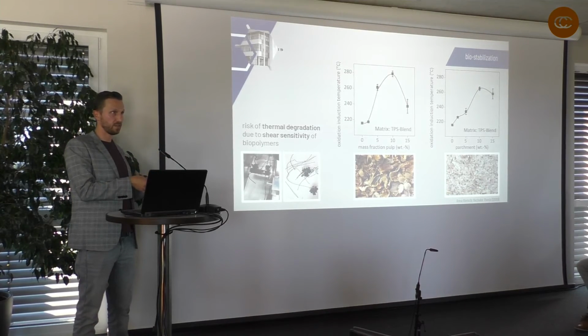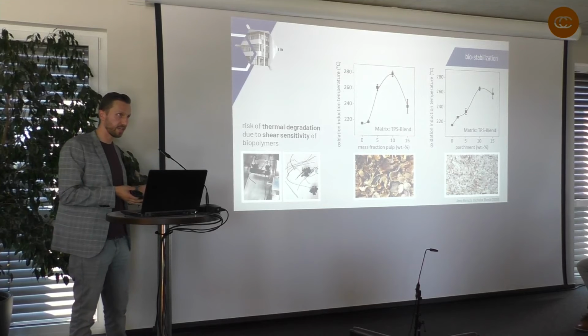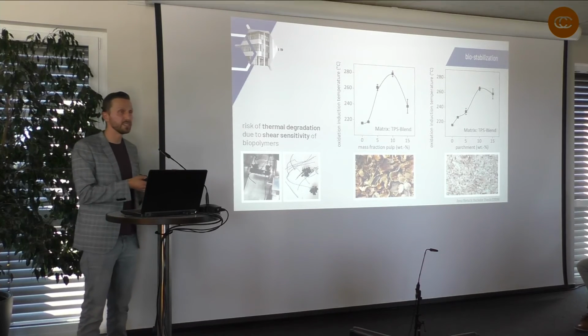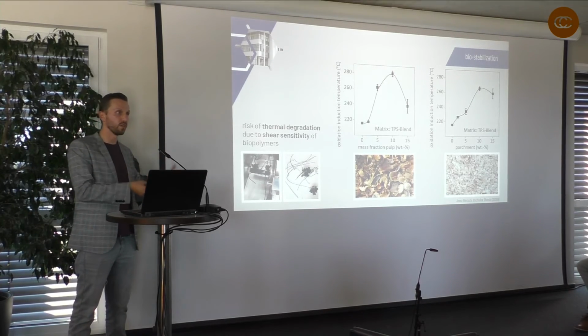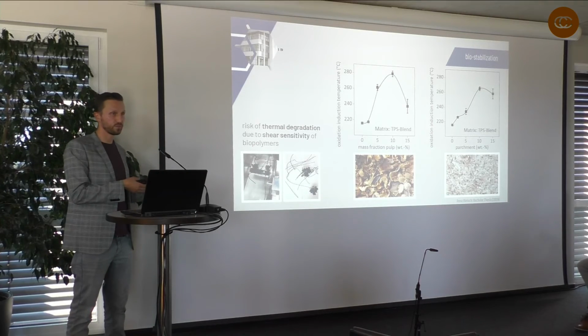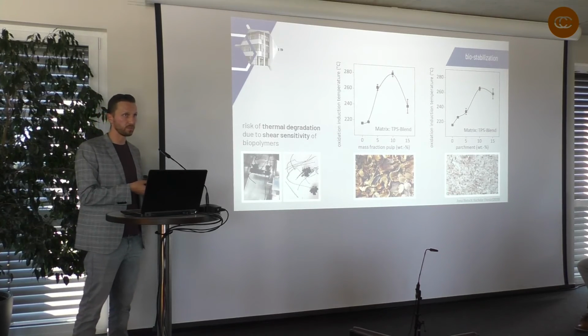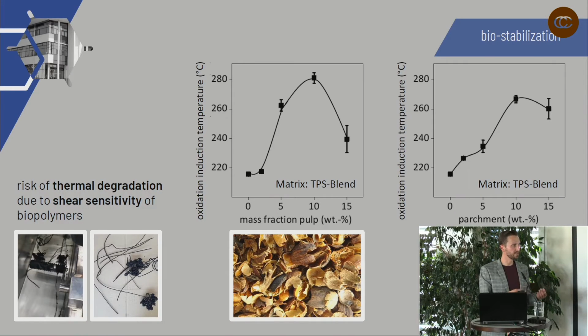This means we can process this polymer at higher temperatures, because this is one of the biggest problems today with biopolymers: when we need a certain temperature to bring the material to flow, we can have thermal degradation. That means we destroy the polymer, and the biopolymer starts to get brown due to this degradation process. With the help of these natural stabilizers, we can increase the temperature and nothing will happen to the biopolymer. So it can act as a thermal stabilizer.